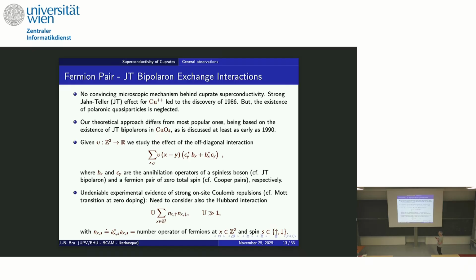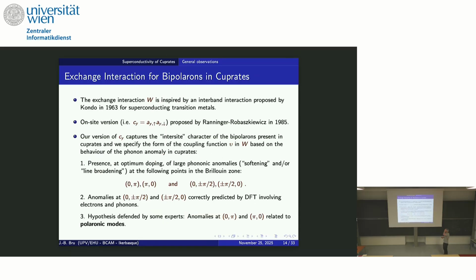And there is one thing that we should not avoid, which is where this U at the beginning is, because these systems are strongly correlated. If there is a Mott phase, if there is a Mott insulator, it means that there are no itinerant electrons that don't want to move. It means that the Hubbard interaction is sufficiently strong. So in your pictures, the Hubbard repulsion should not disappear. It should be there, it should be taken into account. This is quite important. If you don't have this, then you don't get the results that I am going to present at the end about quantum prediction.